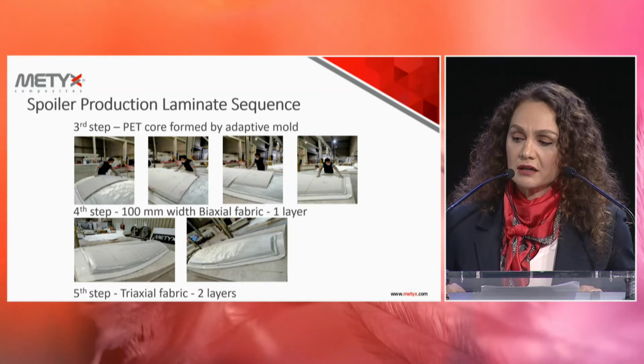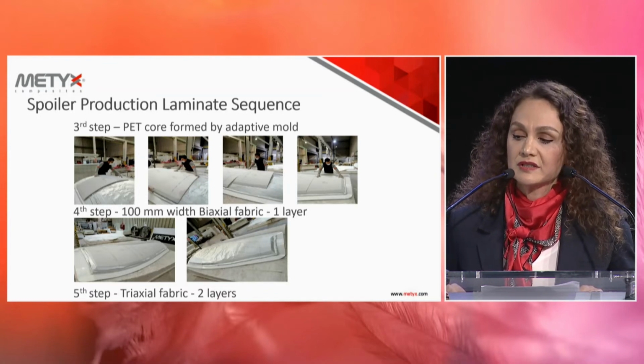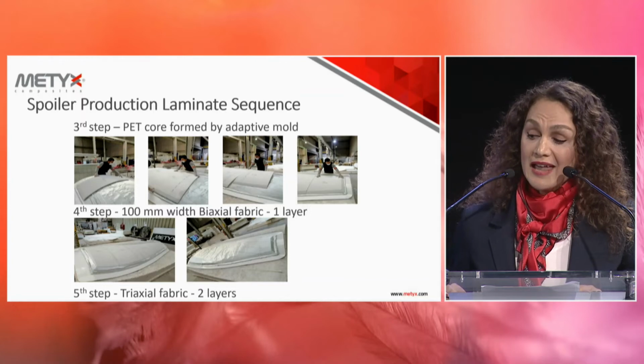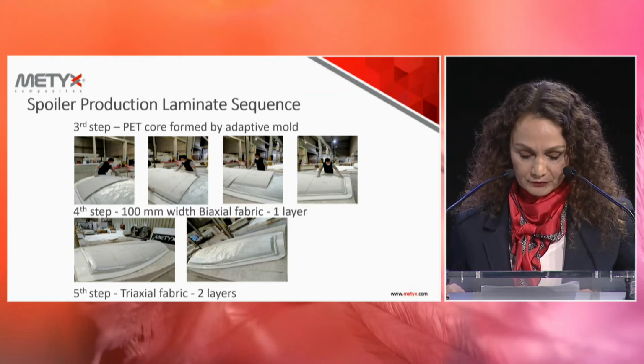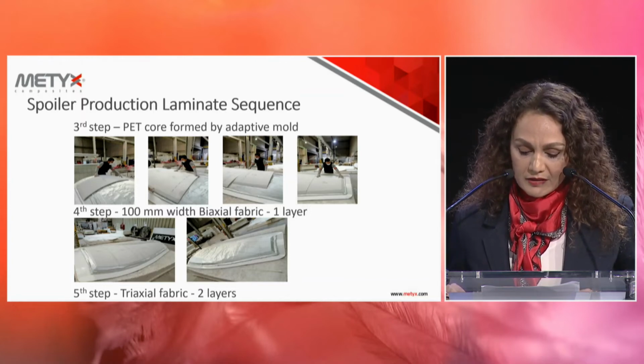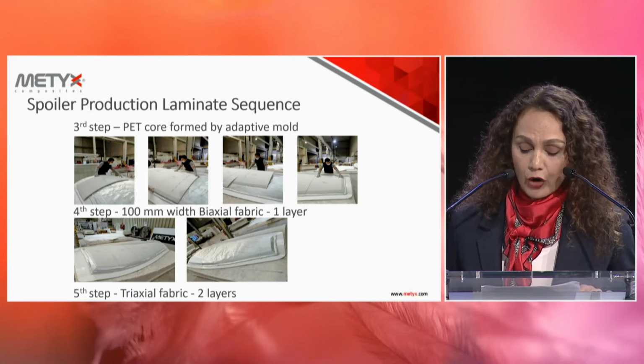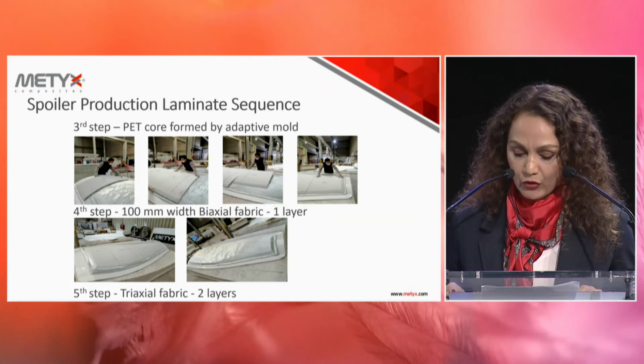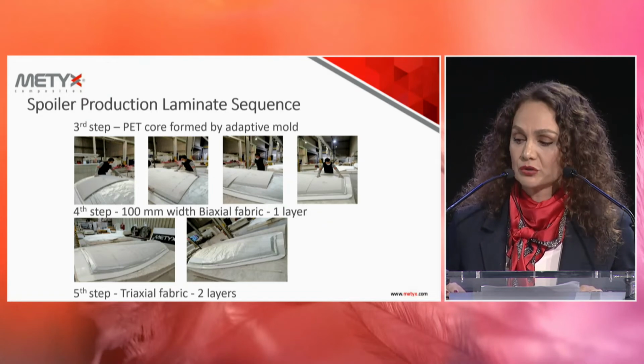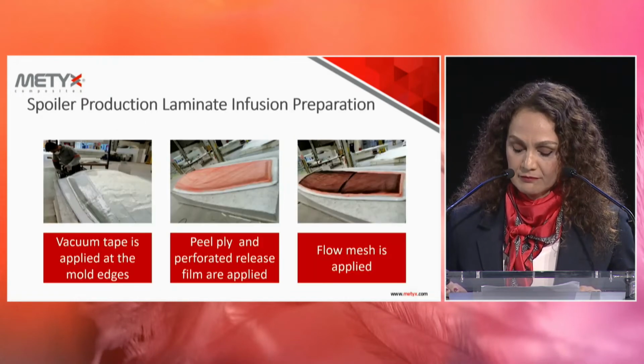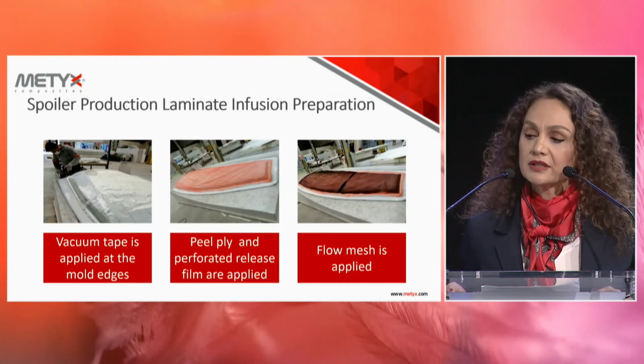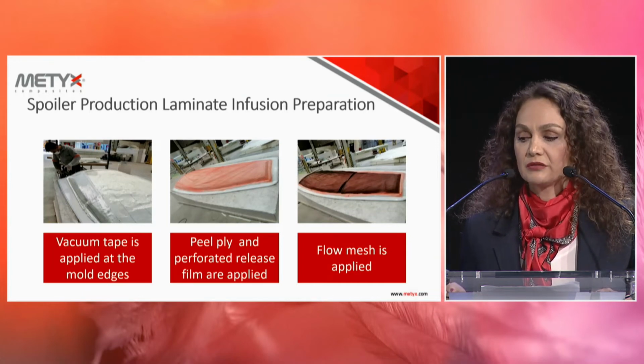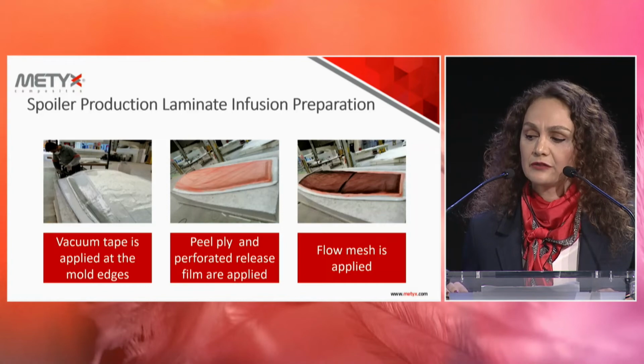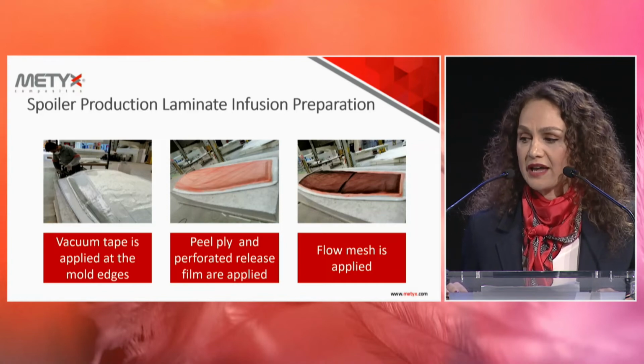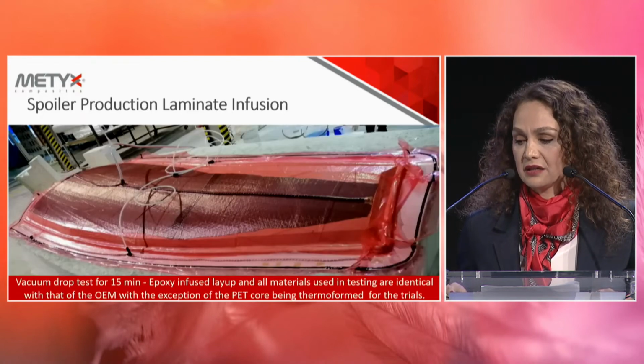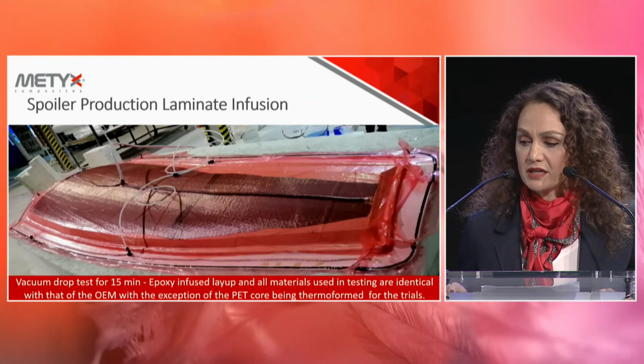So you can see on the top 4 pictures, we lay down the thermoformed core. There's no pushing into forming a shape. We don't use any force, and it lays down quite nicely on the tool surface. We just use the classical laminate infusion preparation. We applied vacuum tape, peel ply, perforated release film, and flow mesh after that. And then it's a classical lamination with the epoxy infusion system.